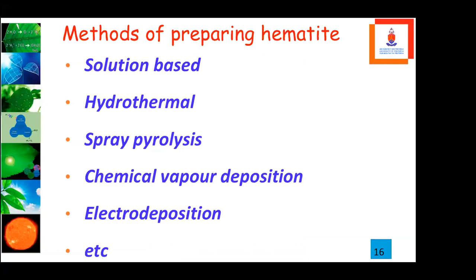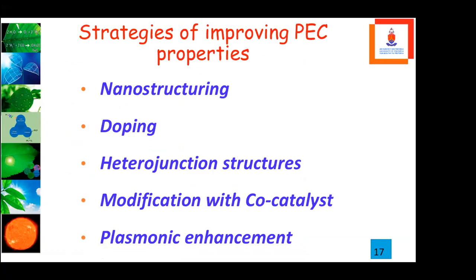We have made this iron oxide using solution-based methods, hydrothermal method, spray pyrolysis, and all of that, and we have built these in our lab. We have found that if you use nanostructuring, doping, heterostructures, modification with co-catalysts, and plasmonic enhancement with metal nanoparticles, we are able to improve photocurrent using hematite.